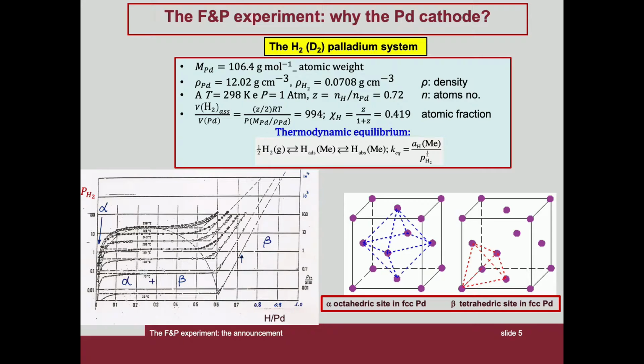The absorption of hydrogen into palladium is due to migration into the interstitial sites of the face-centered cubic lattice of palladium. Two types of sites are occupied as a function of the hydrogen-palladium ratio: octahedral sites, 1 per cell, constituting the alpha phase, and tetrahedral sites, 8 per cell, which make up the beta phase.